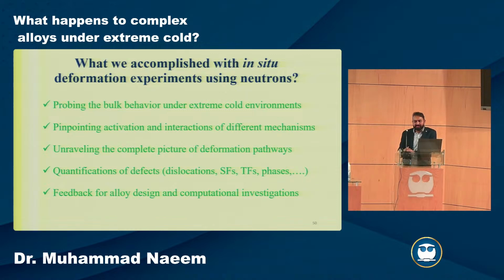So probably because of dislocation interaction, because aluminum has very high stacking fault energy, so you cannot activate another mechanism. So it has to do with dislocation dynamics then. How dislocations, their character, can change, like it can be screw, edge or mixed type. It can also be about dislocation cells forming, and also that we accumulate more dislocations at low temperature. So ultimately everything is linked to dislocations, but there is no simple answer to that. It's very difficult, because different materials behave differently, even single elements are showing an increase in ductility.